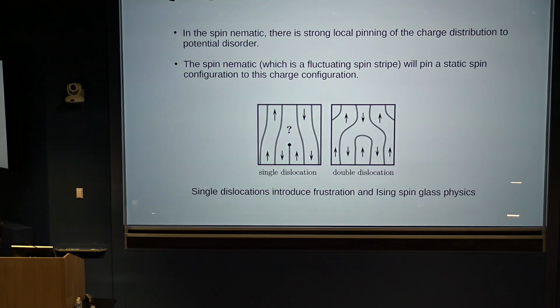So the nematic phase is shown here as something which has a direction, and it has topological defects. No, this is actually the spin stripe order really. But this is at zero temperature, or this is something which occurs only at constant? This would be at zero temperature, yes. Very good. Because I was worried about what happens to magnetic order at non-zero temperature. Disorder, yeah, of course, the disorders.